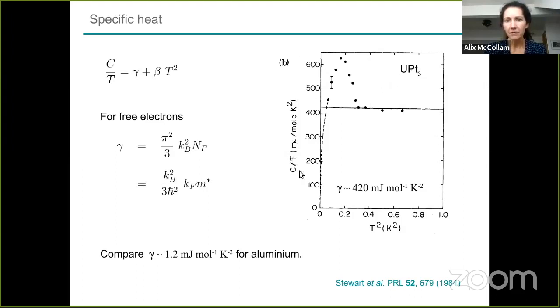This is then C over T as a function of T squared. So there's no contribution proportional to T squared here. It's at very low temperature. And then you see that this gamma coefficient is just a constant, and it's around about 420 millijoules per mole Kelvin squared, which is extremely high. If you consider a regular metal, some kind of good metal like aluminium, it's only 1.2. So this is a huge enhancement. And a number of other materials like uranium ruthenium-2 silicon-2, or cerium copper-6, this can be even higher, up to 1,000 or even a bit more.